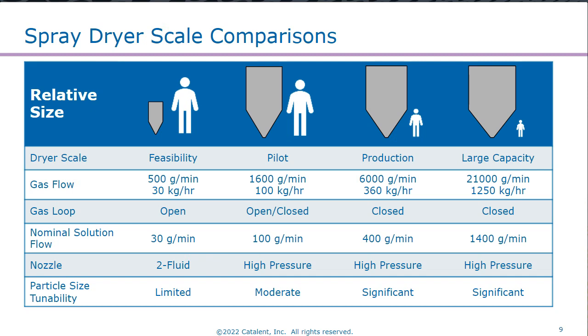on the surface. As we move into phase 1 and pilot scale batches, it's often a time where we transition into closed loop recycle nitrogen. So we need to keep an eye on how that impacts the relative saturation of solvents at our dryer outlet. And we're also switching to high pressure nozzles, so we have to be careful about how we select that nozzle to ensure we're creating droplets of the right size for the particles that we want. Late phase, we're often looking at switching to production or even very large capacity scale spray dryers. These dryers have large drying volumes, which do allow us to have a little more flexibility with the way we're using our nozzle to create droplets that are larger and dry slower because they have more time until they impact onto the wall of the spray dryer or outlet piping.